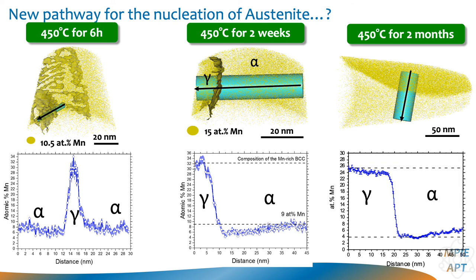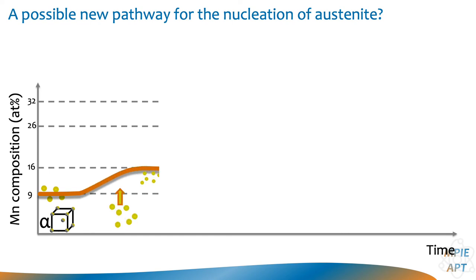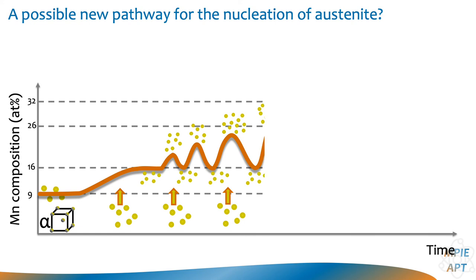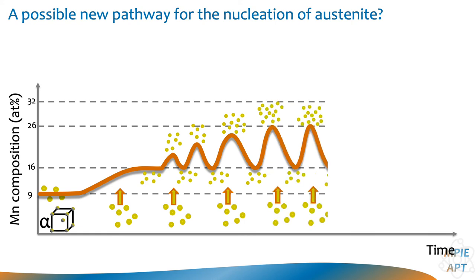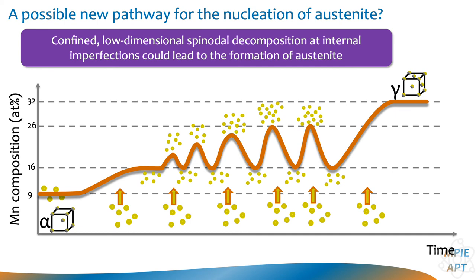As we keep proceeding with heat treatment — for two weeks for example — these gamma regions at the interfaces keep growing, and the fluctuations in segregation to the boundary disappear. After two months, we start to have large gamma particles that have grown. To summarize: as heat treatment proceeds, interfaces get progressively populated with more manganese. The iron–manganese system has a miscibility gap, so we think that locally, as the composition increases, spinodal fluctuations form. At some stage the composition gets high enough that gamma becomes the most likely phase to form, and then it keeps growing as heat treatment proceeds.